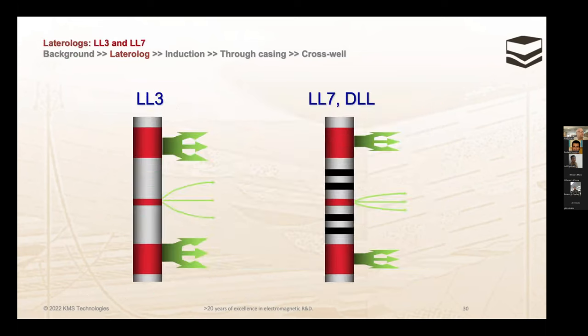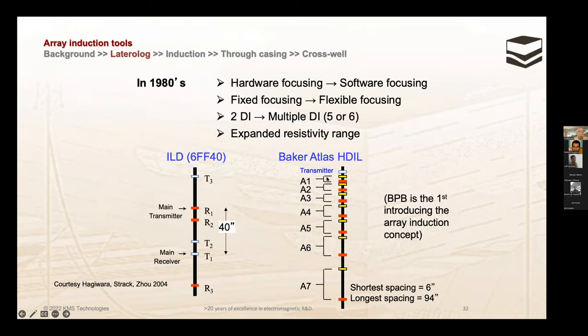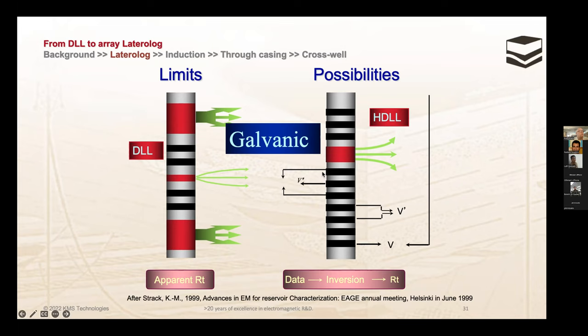Now, this is my computer. These second differences are very important, which are here. Second difference are the difference between two differences. So you measure this voltage and then the difference between two voltages. Because this is directly proportional to the current flowing away from the logging tool into the formation. So measuring all the voltages, the difference between electrodes, and the second difference allows you to do exactly what you can do with hardware, but much more accurately by doing software focusing.